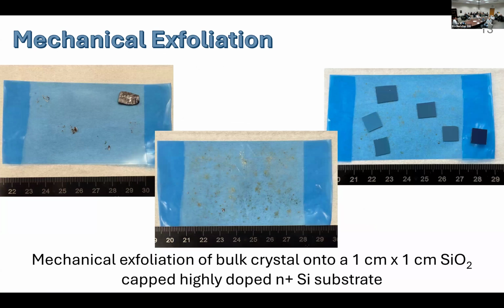So to start off, to isolate our layers, the first thing that we do is called mechanical exfoliation. So this involves dabbing a bulk piece of crystal onto a tape because, again, they're held together by weak van der Waals forces. By folding the tape and peeling it apart, we can peel apart these individual layers. Then we place our substrate consisting of the metal gate and the oxide over this tape, heat it up at a specific temperature for a specific time on a hot plate, release it, and then slowly peel it off to ensure that the flakes don't crack when you peel apart the tape.